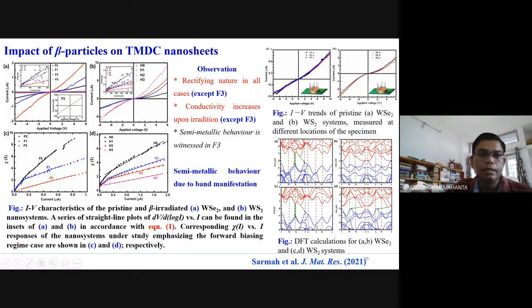So this was showing metallic character. IV was like a simple straight line. However, in case of WS2, all are still showing rectifying behavior. Why is it so? We thought probably after irradiation, this WSe2 is going towards semi-metallic response. Semi-metallic response means there should be an overlapping of valence band and conduction band. So considering that, beta irradiation, high dose beta irradiation can remove some of the chalcogen vacancies, selenium atoms. So therefore now it is no more WSe2, but WSe1.5, 1.6, etc.